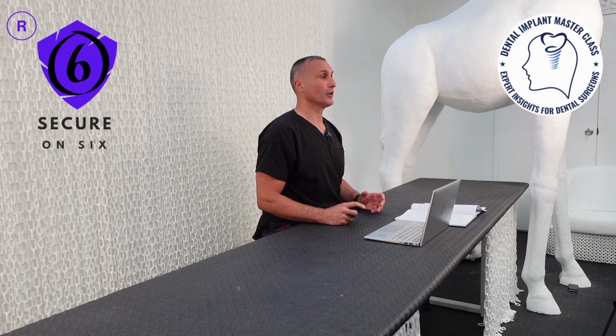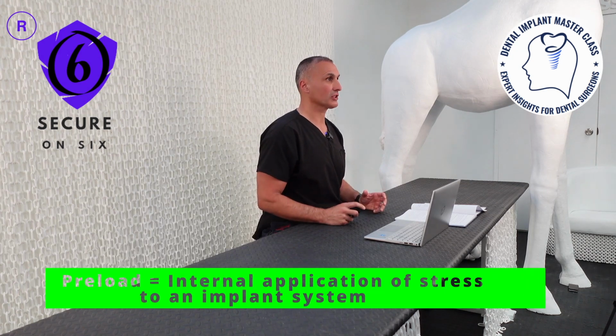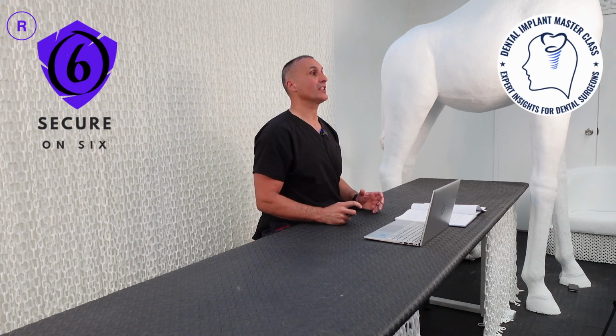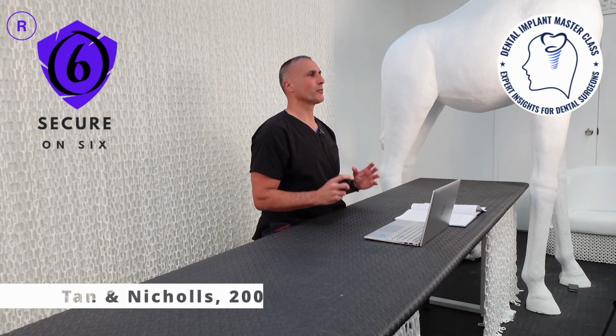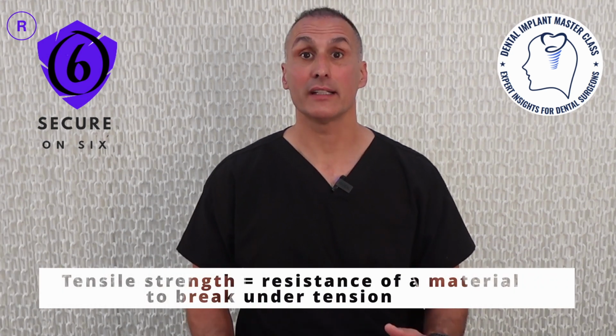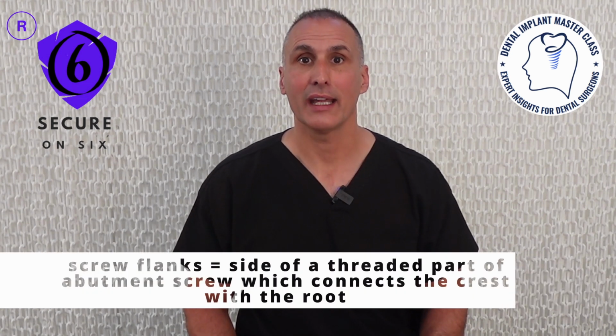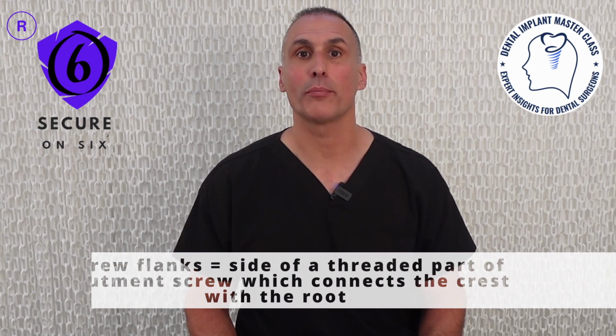Excessive bending refers to a force that can lead to the material failure of the abutment screw. Screw joint preload, defined as the clamping force required to maintain the integrity of the screw joint, has been reported by Tan and Nichols in 2001. The torque applied to the fastening screw is converted into tensile stress in the screw shank, an equal and counter compressive force that holds the two implant components together. The opening or loosening of the screw joint, particularly between a gold cylinder and abutment, has been identified as the primary cause of gold screw breakage.